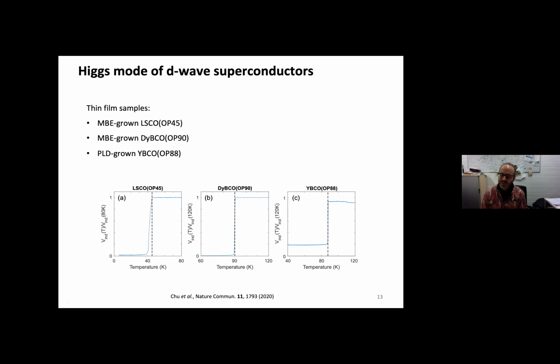So in the following, we will stick now to this drive of the system, and we will now look at different classes of superconductors, and we are taking both single-layered LSCO samples, but also double-layered systems like BSCCO or YBCO superconductors. And we will stay now most of the talk in the optimally doped regime, so that for the people that work in superconductors, this is a regime where we don't expect a strong influence of competing orders like charge density waves, pseudo gaps, and so on. So here we want to look at the pure superconducting response of the material.